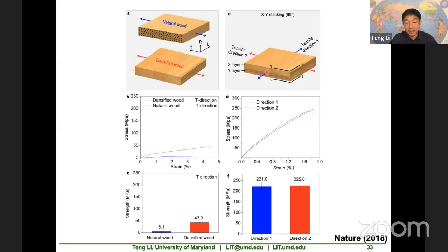So we laminate two layers of densified wood at 90 degrees. So this is going this way, the bottom piece's fiber is going this way. And this bilayer, if you do the tensile test, shows a rather similar tensile behavior in two perpendicular directions with a tensile strength around 200 megapascal, which is not bad at all in comparison with natural wood, still many times higher.